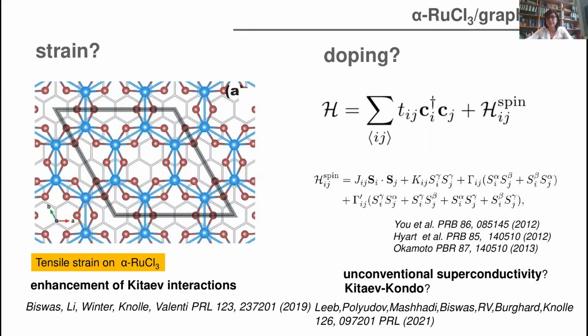Now, what is interesting in the calculations is that we tried many cases to see which is the most stable, and by doing this heterostructure, alpha-ruthenium trichloride gets strained. Even though there is a big lattice mismatch, it needs to find the most stable configuration. And this type of strain enhances the Kitaev interactions.